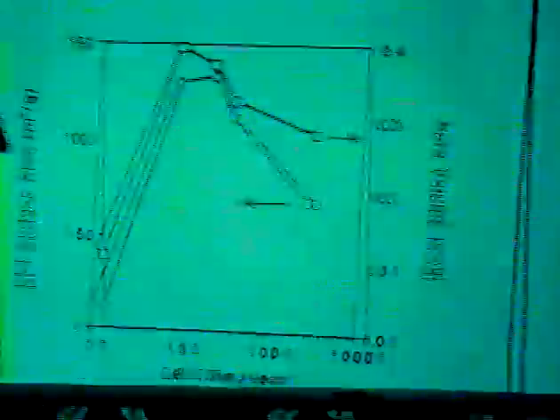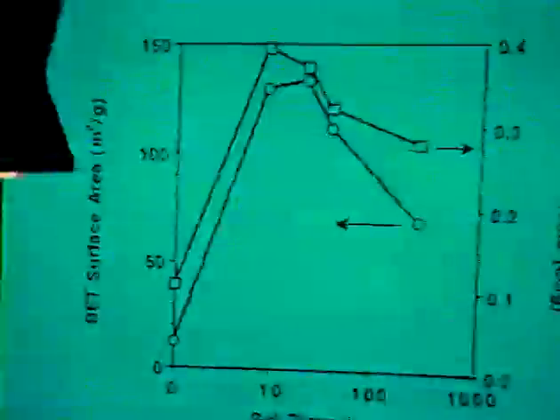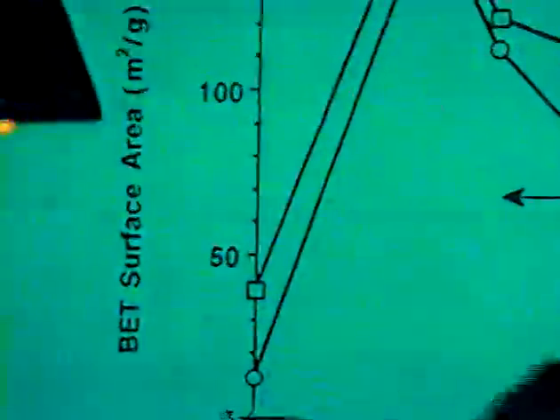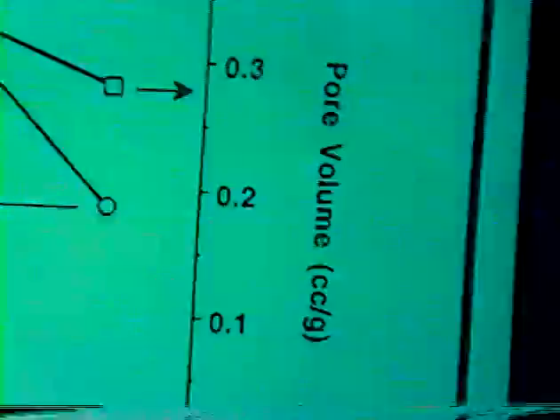Now, what I'm plotting here is the surface area as a function of nitric acid. And I showed you already that nitric acid is also affecting the gel time. So of course one can plot the surface area as a function of gel time directly, in other words, using gel time as the variable. And when you do that, you will again see this maximum.